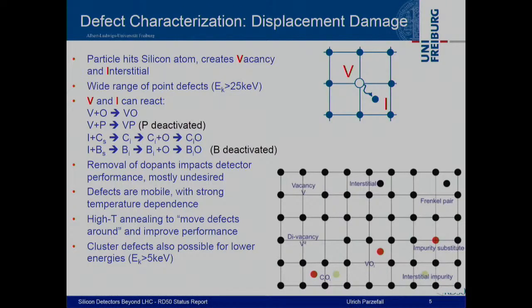Let's start with defect characterization. So what happens if you have some hadron hitting silicon at a lattice site: you actually kick out the silicon, you create a vacancy and an interstitial, and you get a very large range of point defects that can happen when you have enough energy.